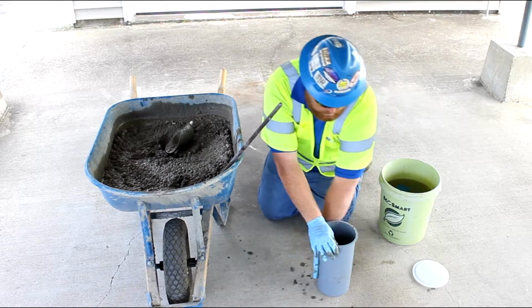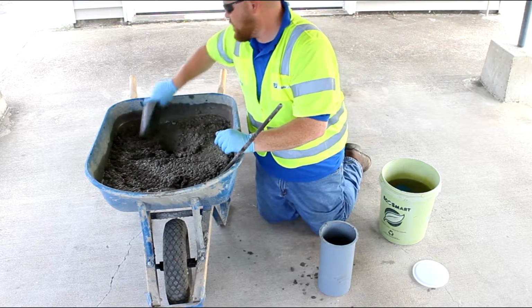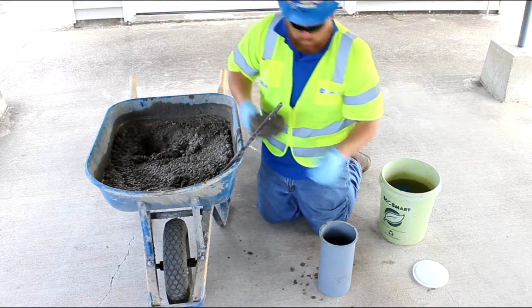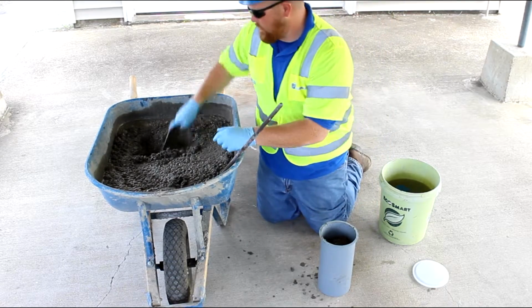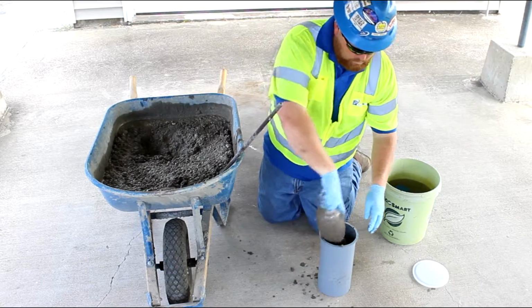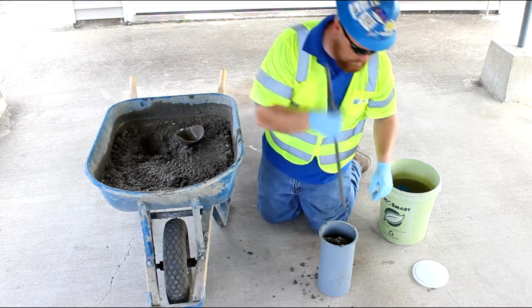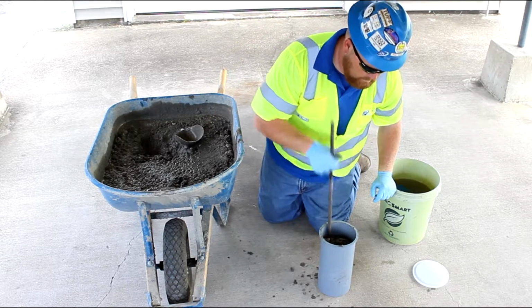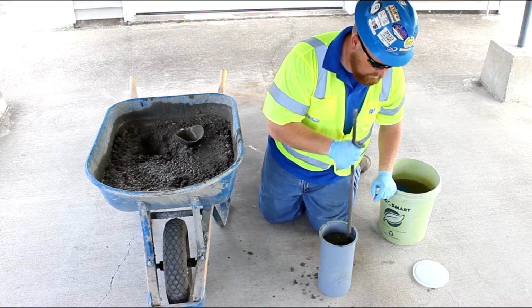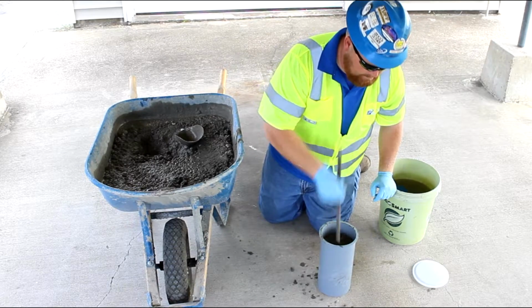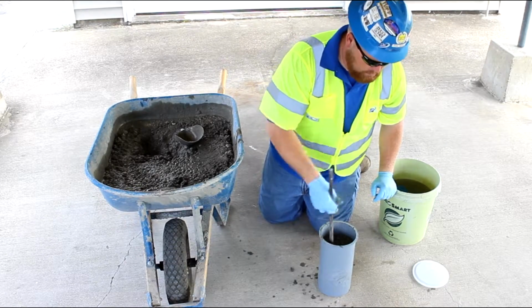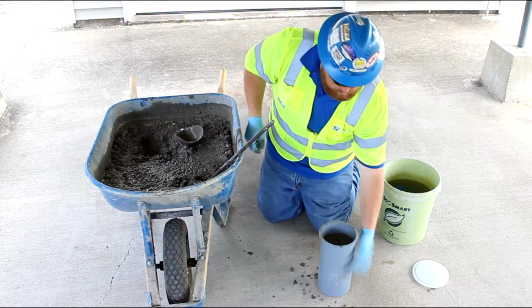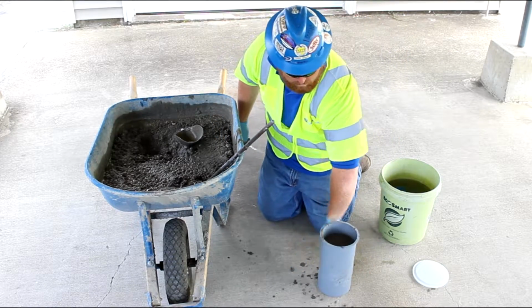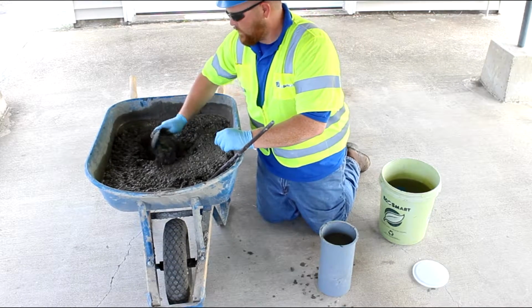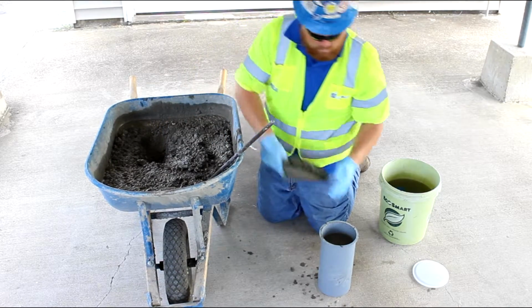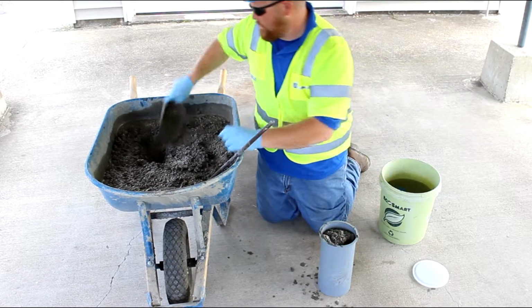While rodding the first lift, rod the layer throughout its depth using care not to damage the bottom of the mold. For the second and third lifts, rod the layer throughout its depth and approximately 1 inch into the previous lifts. After rodding each lift, tap the outside of the mold 10 to 15 times lightly with an open hand to close any holes left by rodding and to release any large air bubbles.